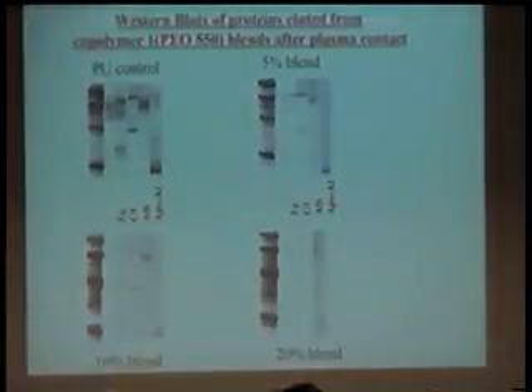So again, we're looking at the best of the bunch here, the PEO-550. Molecular weight. This is the control with no PEO, the 5% PEO, the 10%, and the 20%. And the lanes are, these are standards, of course, and the lanes are this is fibrinogen, this is C3, albumin, and ApoA1. And I don't want to go into detail again on this, but you can see that the densities, this is controlled quantities of protein and eluate loaded onto the gels. There's a high density of staining here. It's less when you get to 5% blend, even less here.